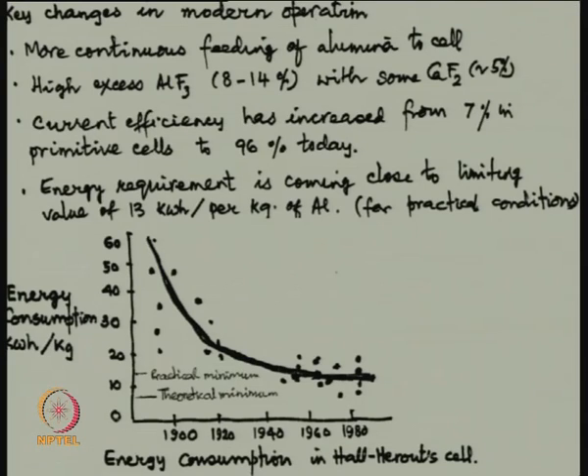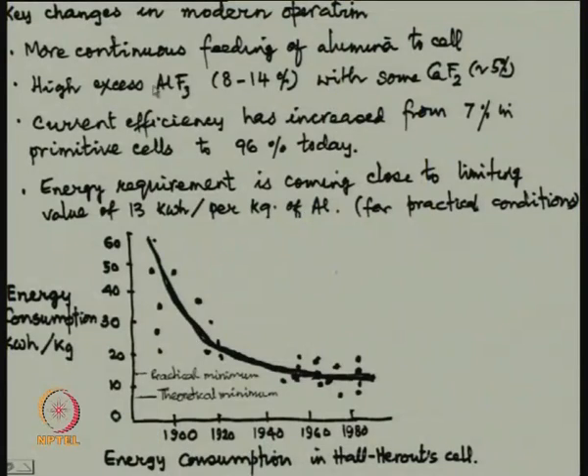Now, what are the key changes in modern operations, say compared to what happened about 100 years ago? First of all, they have now found cells where there will be continuous feeding of alumina to the cell, continuous removal of aluminum, higher excess of aluminum fluoride, a lot of aluminum fluoride excess is being added, and a lot of calcium fluoride excess, 5%, is being added. Current efficiency in the beginning was 7%, has gone up to some 96% today, means only 4% of the current is going into reactions that we do not want.